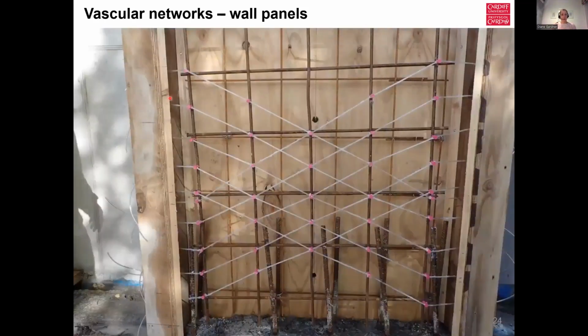The placement of the vascular networks can be seen on the slide at the moment, whereby we use these pink 3D printed connectors to make sure that we had good continuity at the points where the channels crossed each other. They were then extended to the side where a series of packers were used to be able to place the healing agent within the system.